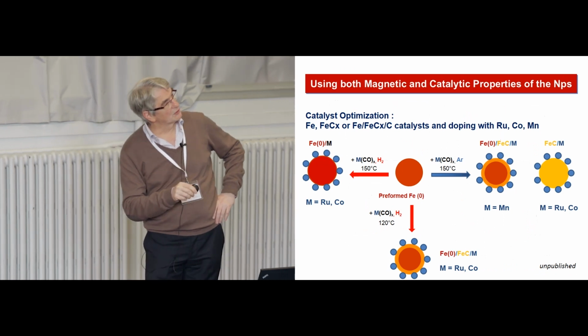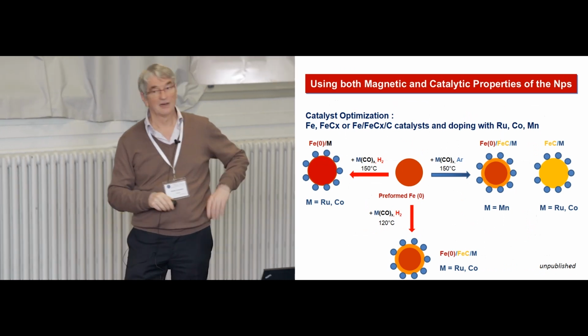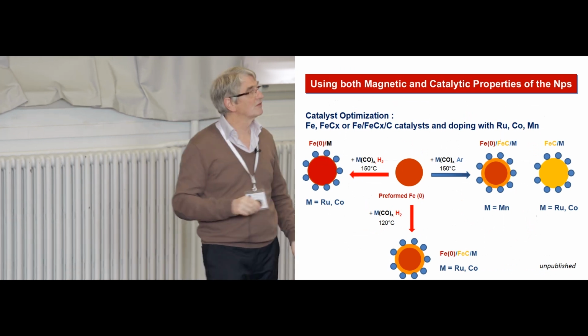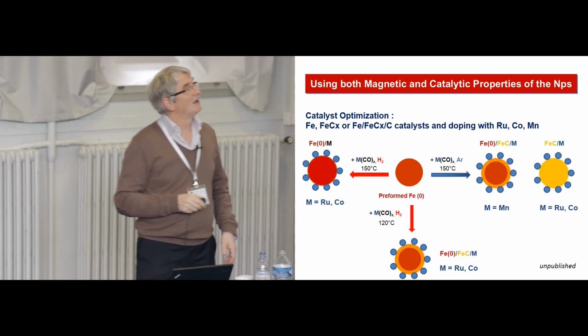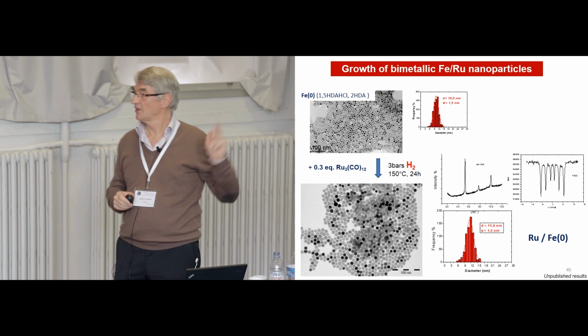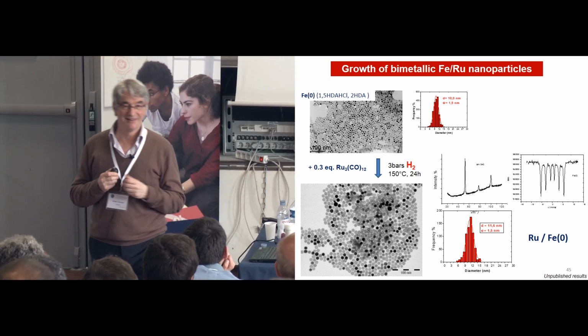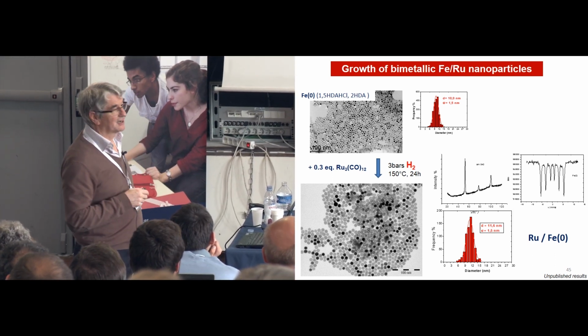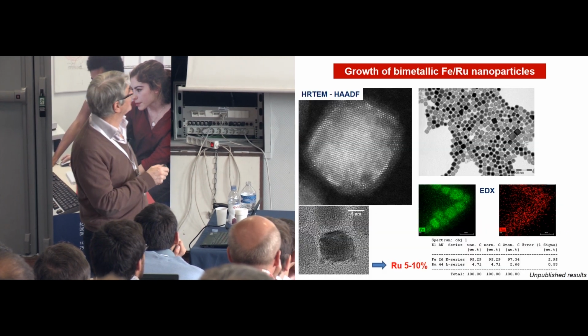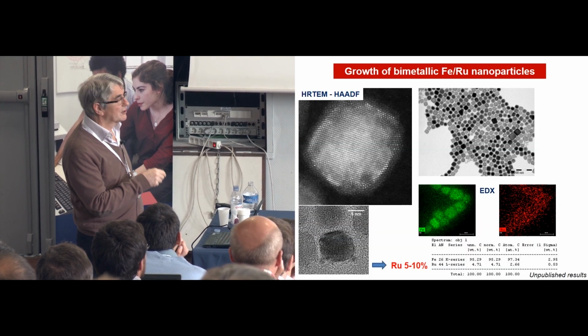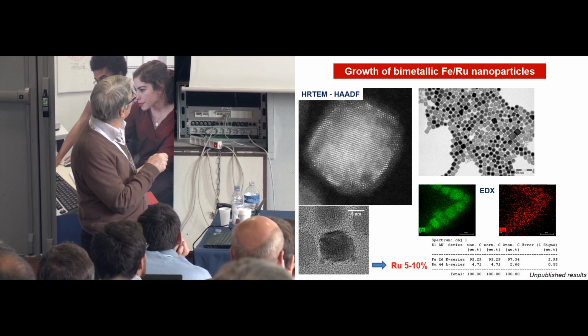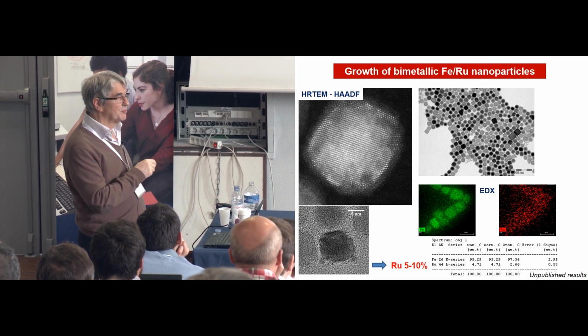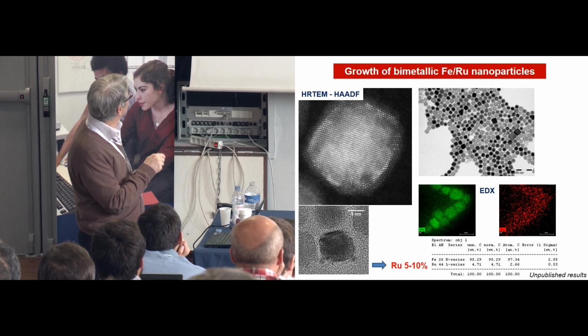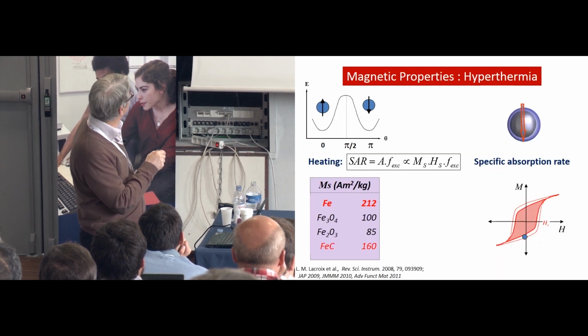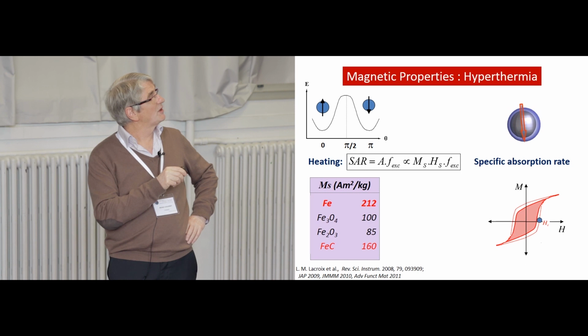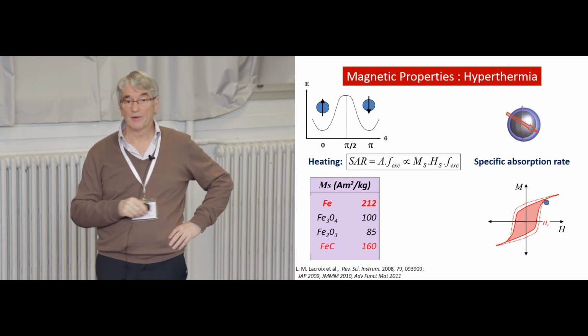We can see that those cubes by EDX have about 5% ruthenium on the surface. And then you can admire, I think it's a very clear physics demonstration here. When you turn the magnetic moment, you will pass a barrier because these particles are ferromagnetic, and you have two stable positions, and a thermal barrier.